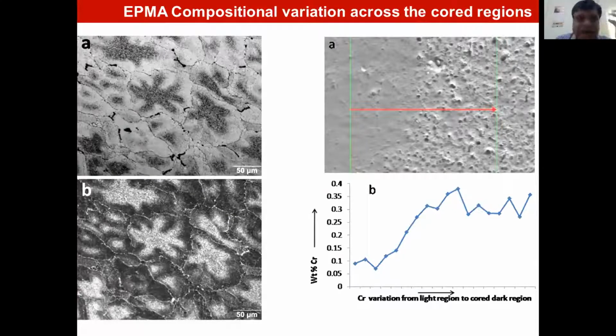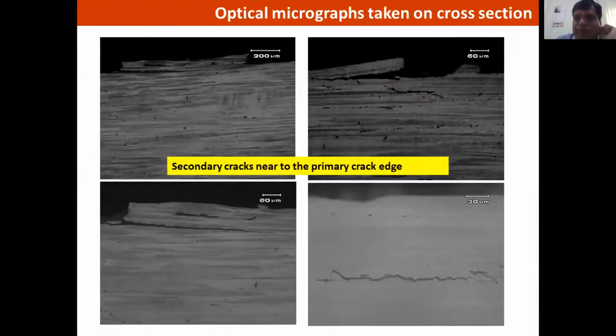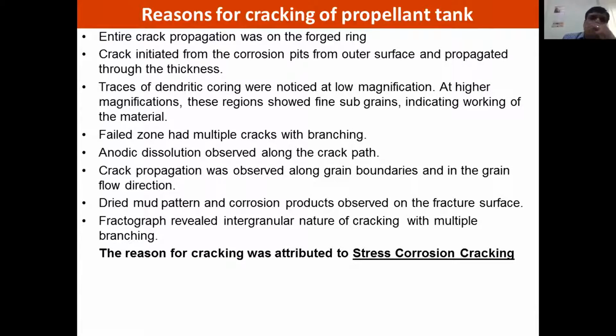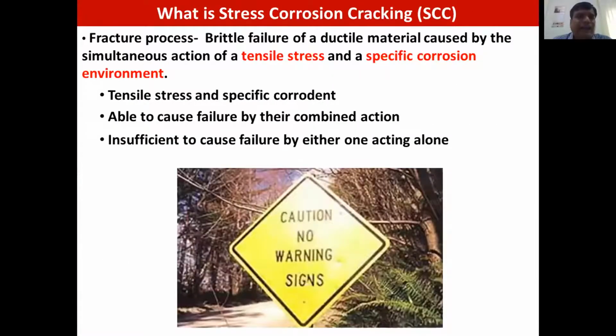Subsequently, this material has been removed from our list of materials in use. We changed it to aluminum copper Li alloy AA2219, and we did extensive analysis on this particular hardware. There is a difference in the chemical composition across these flowery patterns. As you can see, there is segregation of chromium, and of course these are the optical microstructures with the cracks running parallel. We attributed the failure to stress corrosion cracking based on the fractographic observations, the microstructural observations and the features seen on the failed component. Now, stress corrosion cracking comes without any warning signs. That is the most dangerous part, and it is brittle failure of a ductile material caused by simultaneous action of tensile stress and a specific corrosion environment.